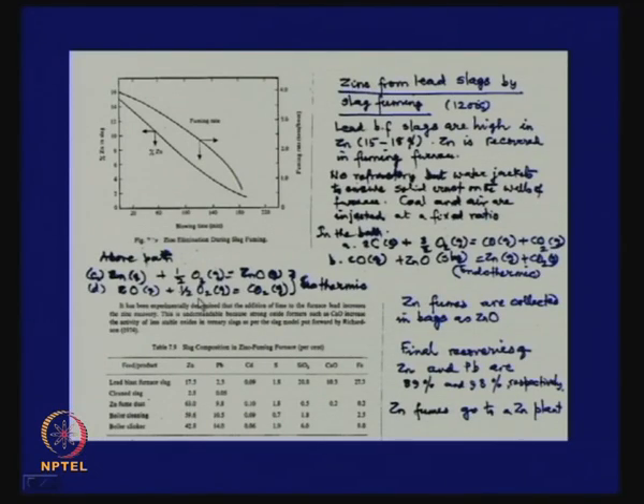Now, during my discussions, you must have heard me say the words zinc recovery from lead slags, because even in the slag that comes out of the imperial smelting process, some zinc will come out. A lot of zinc will also come out of the lead blast furnace, and lead blast furnace slags normally contain 15 to 18% zinc in solution in lead slags. How do we recover that? Because it is there as some kind of a silicate.